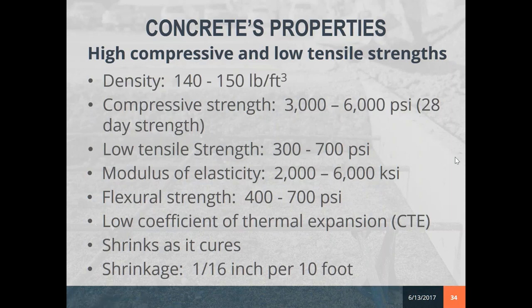One thing to note is that concrete will shrink, according to ACI and other codes and studies, approximately a 16th of an inch for every 10 feet. So this is what we're working on in order to control: the shrinking and cracking, putting the cracks where we want them and not letting it randomly happen, reducing the amount of cracks that show up in our concrete facilities.